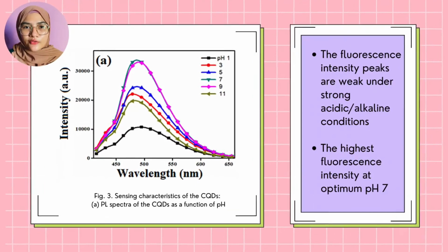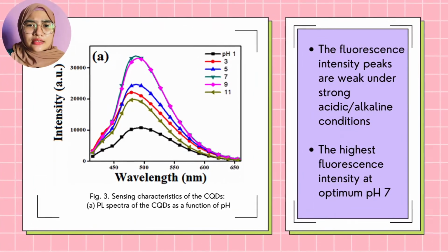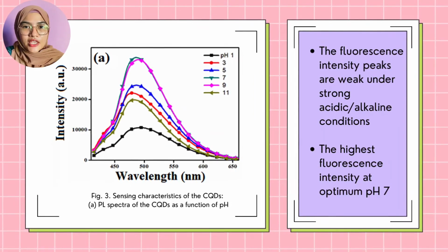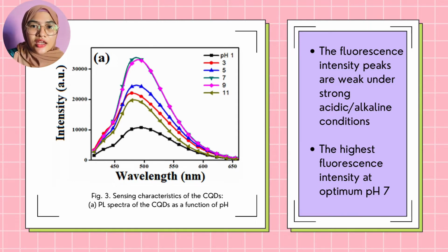Next is the pH dependence of CQDs' PL emissions. To explore the pH effect on sensing potential of CQDs, PL intensity for the CQDs was monitored at different pH values, which are 1, 3, 5, 7, 9, and 11. As shown in the figure, under strong acidic conditions or under strong alkaline conditions, the fluorescence intensity peaks were weak. Under strong acidic conditions, the CQD surface was favorably occupied with carboxylic acid groups. In contrast, under strong basic conditions, the amine functionality becomes dominant on the CQD surface. The highest fluorescence intensity was observed at pH 7. Therefore, the whole sensing platform was adjusted to a neutral pH value for optimum detection of iron 2 plus ions.